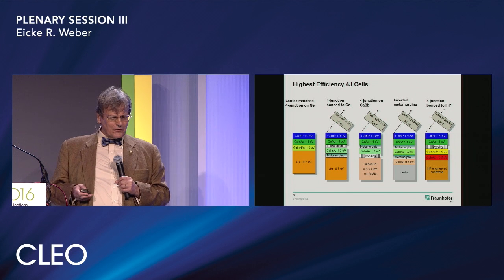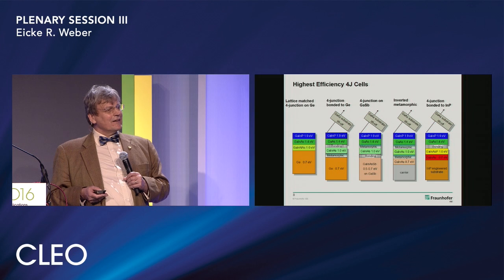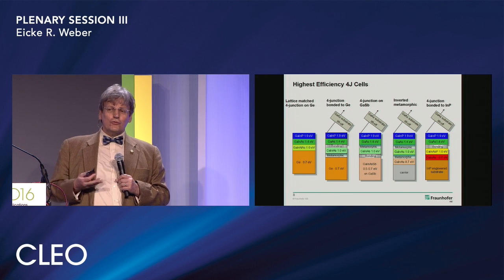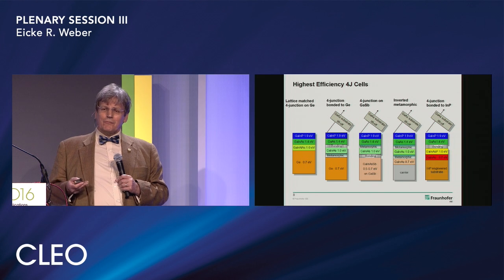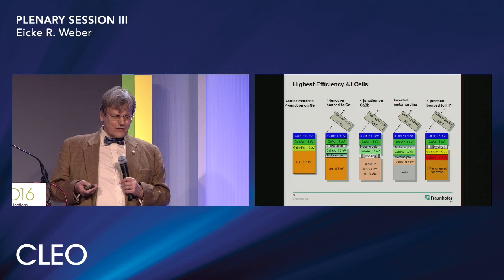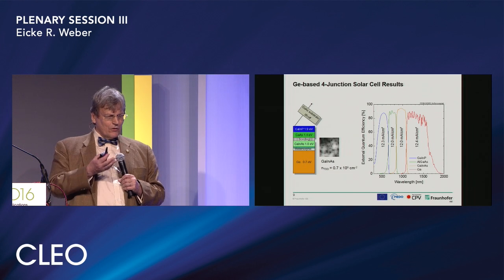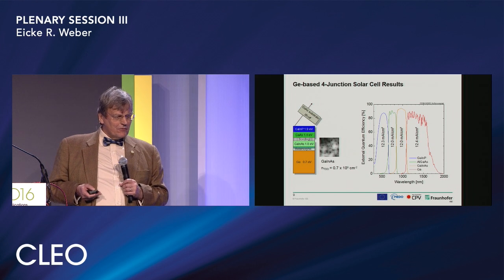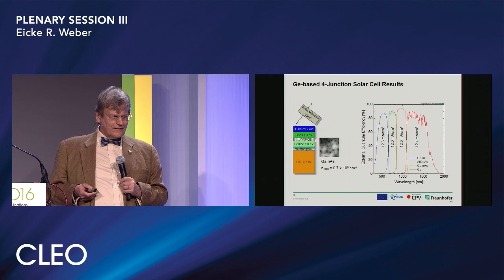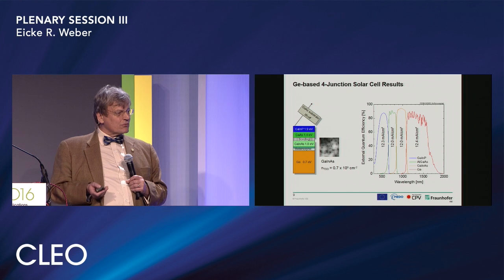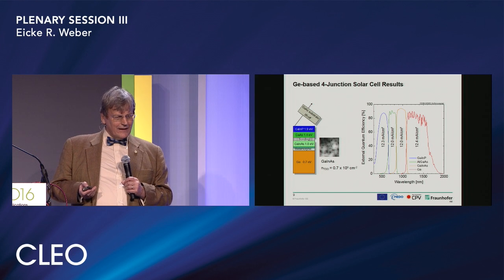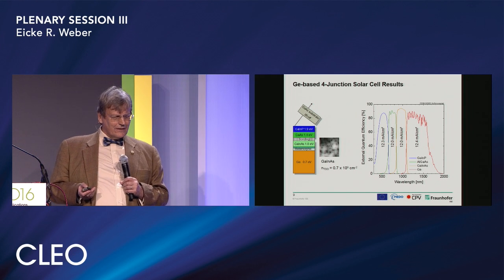This is what I will talk about a little bit more, where we can grow structures on two different substrates, optimize them, and then bond them together, forming one structure and at the end one solar cell. So this is the germanium-based 4-junction solar cell. You see the spectral efficiency data from each of the different layers.